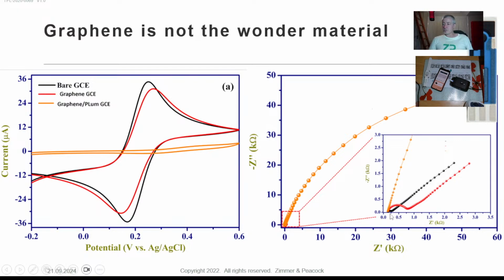spectroscopy data. Now they're showing their data here in what's called the Nyquist plot, and I can see really carefully that with the graphene, the reason you get the best cyclic voltammetry is because you've got the smallest charge transfer resistance. And I think the author of this data knows this kind of stuff. This is something known to them. That's why they've shown it to me. But it shows me here that you've only got like 100 ohm type of resistance, your charge transfer resistance.